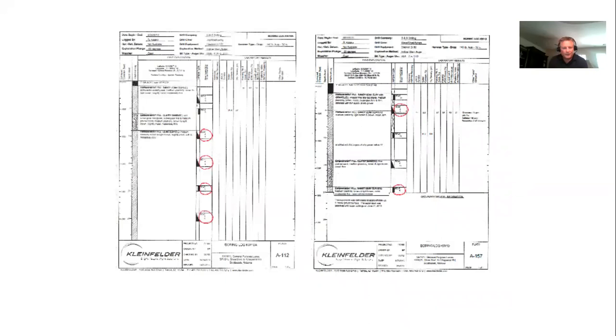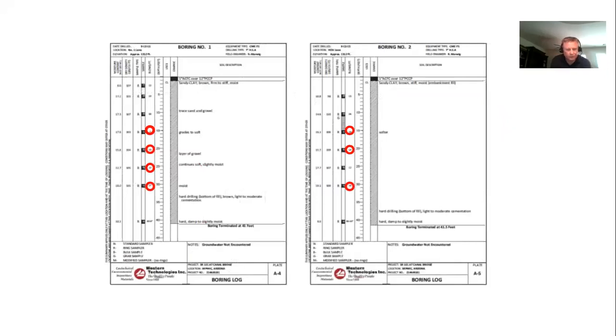So the red are really indicators of bad conditions. We've got bad conditions on that first boring from 10 to 25 feet. And then the other one shows it's softening at 5 and 20 feet. And then the other two logs, which are maybe a little easier to read, those are not R values, those are ring samples. You convert those to SPTs and you get values anywhere from about 3 to 11. So, they're pretty soft. Again, I think this material was probably put in fairly dry, got wet at some point, and just lost its strength. And so this is really the zone that we were dealing with, primarily from about 10 to maybe 25 feet.